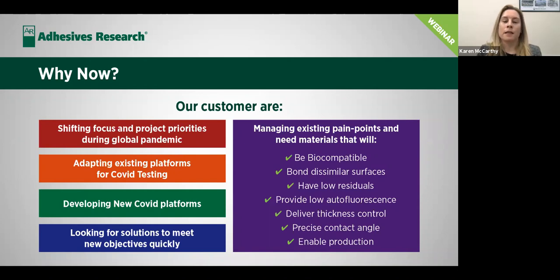Precise contact angle is desirable if the adhesive tape is going to be used to modulate the flow through the chip or the device. For example, if you're looking to speed up the flow of the sample through your device, you're going to need a hydrophilic adhesive with a low contact angle that will wick the sample through quickly. Equally, you might be looking to slow it down somewhat, and then you'd have an intermediate contact angle, possibly a hydrophobic adhesive, in instances where you've possibly reaction chambers within your device and you need the flow to be slow in that area. And then finally, the use of adhesive tapes for device fabrication enables rapid, hassle-free production.